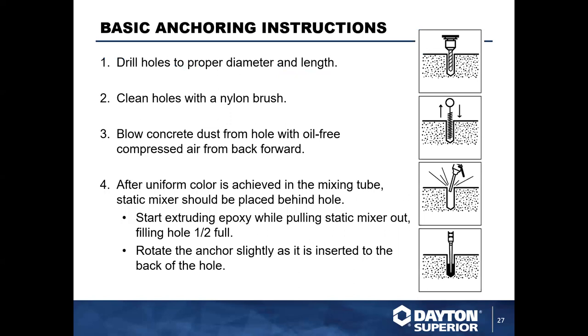Basic anchoring instructions: drill your hole, then clean it with a nylon brush using a circular up-and-down brushing motion. Blow the hole out from the bottom up — not from the top down, as that pushes dust to the bottom and can cause anchoring failure at the bottom of the hole. Insert the nozzle into the bottom of the hole and fill from the bottom up to avoid trapping air.